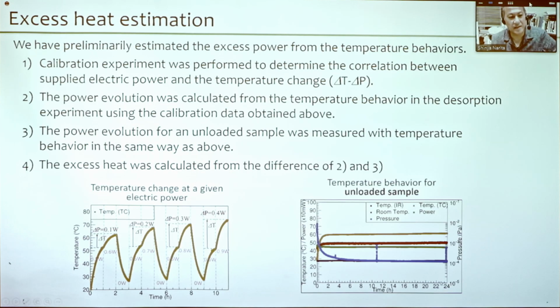Okay, so now from these results, we have preliminarily estimated the excess power from the temperature behaviors. So here's the procedure to estimate the excess heat. At first the calibration experiment was performed to determine the correlation between the supplied electric power and the temperature change. So this left plot is an example for the calibration. We examined how much the temperature increased when supplying a given power to the sample. So then we have obtained the calibration data, the relationship between delta T and delta power. And the power evolution was calculated from the temperature behavior in the desorption experiment using this calibration data, as I showed.